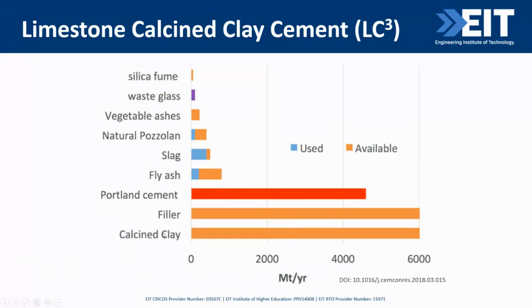We can see from this figure, which shows the estimated availability of possible supplementary cementitious materials and fillers. We can see that the most commonly used supplementary cementitious materials like fly ash and slag are already or almost fully used and cannot be scaled up for use in cement. And furthermore, with increased focus on sustainability, more and more coal power and steel production plants are expected to be closed. So this will further cut the supply of these materials as supplementary cementitious materials.